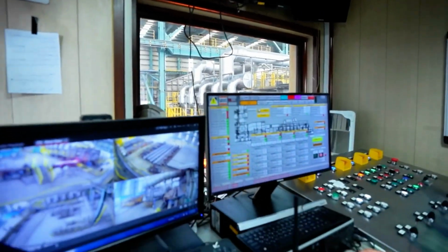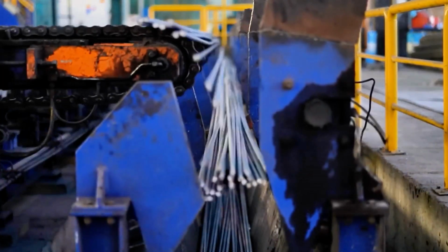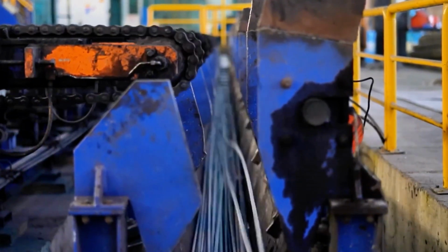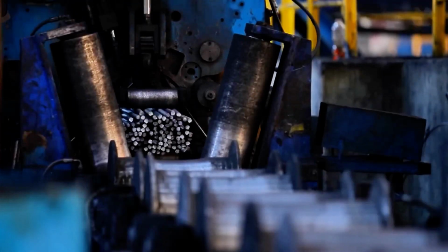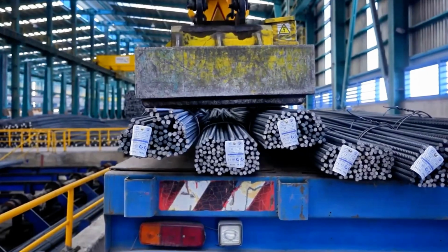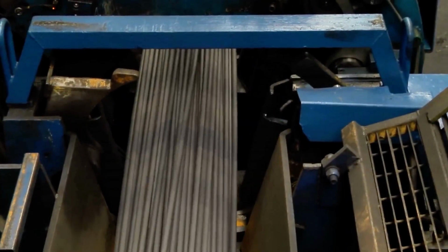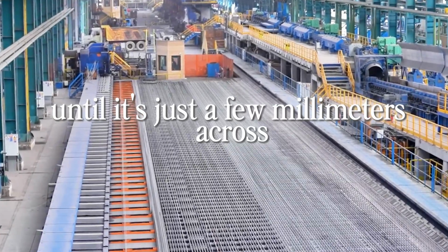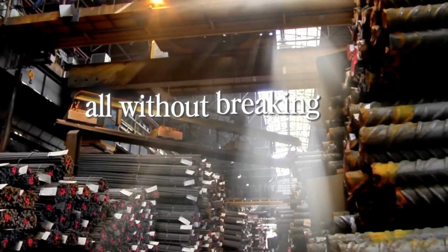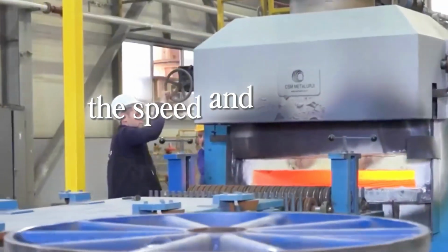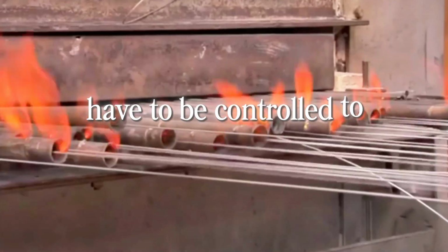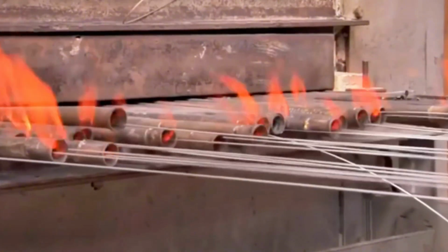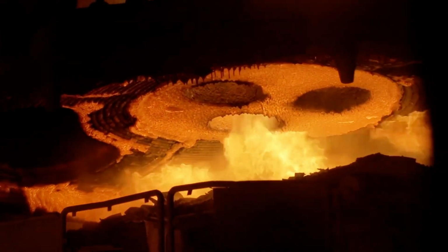The steel is pulled through a series of tungsten carbide dies, tiny openings that gradually shrink in diameter. With each pass, the wire becomes thinner, longer and smoother. Imagine pulling a 2-inch thick rod through dozens of polished steel rings until it's just a few millimeters across, all without breaking. The tension, the speed, and even the temperature have to be controlled to microscopic precision. As the wire stretches, its internal structure changes.